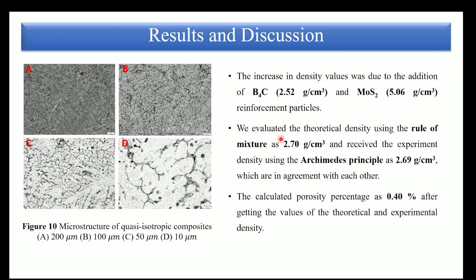Using the rule of mixture, we calculated 2.70 gram per centimeter cube, and the experimental density, using the Archimedes principle, is 2.69 gram per centimeter cube, which are in agreement with each other. The calculated porosity is 0.40 percent, after getting the theoretical and experimental densities.